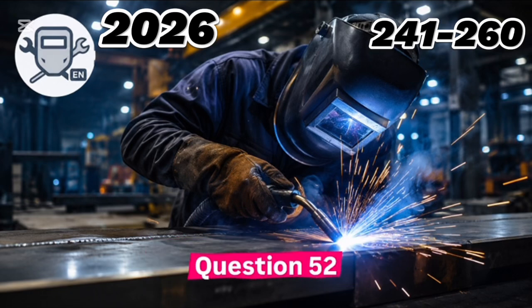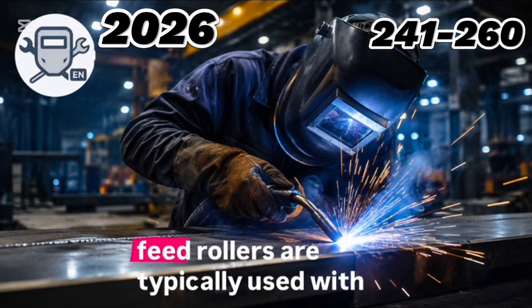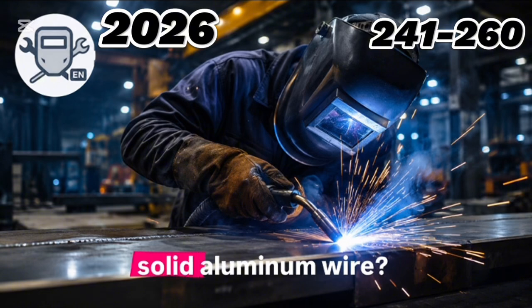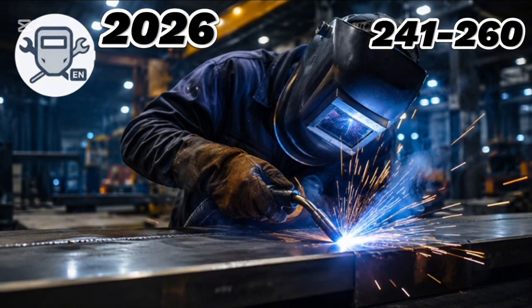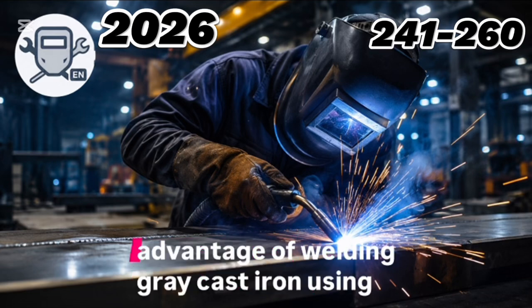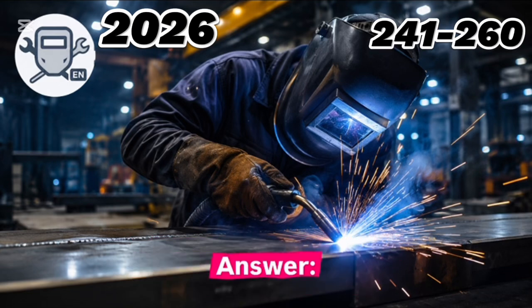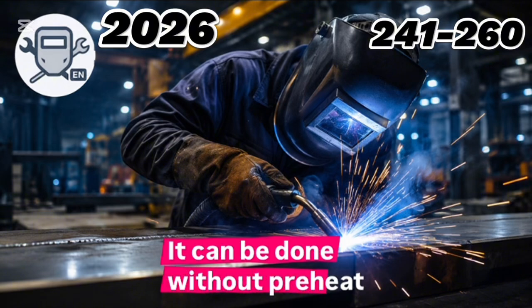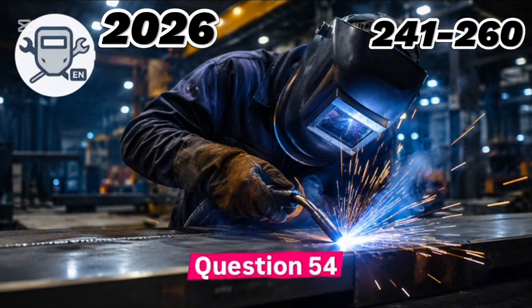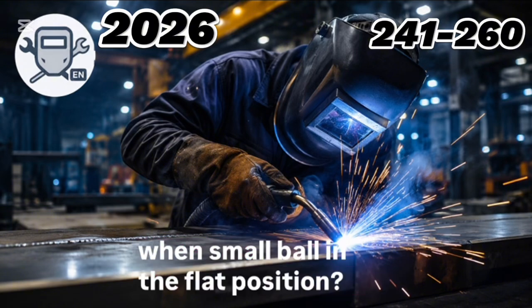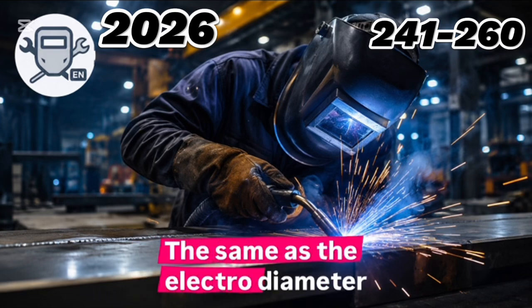Question 52. Which of the following GMAW wire feed rollers are typically used with solid aluminum wire? Answer: U-groove. Question 53. Which of the following is an advantage of welding gray cast iron using SMAW? Answer: it can be done without preheat. Question 54. What arc length should be maintained when SMAW in the flat position? Answer: the same as the electrode diameter.